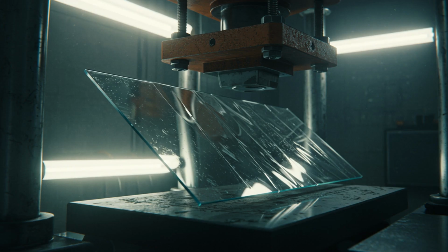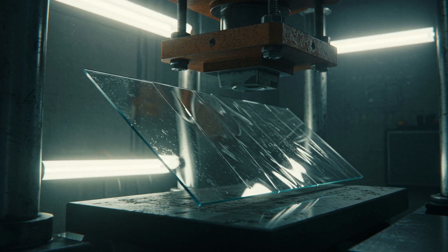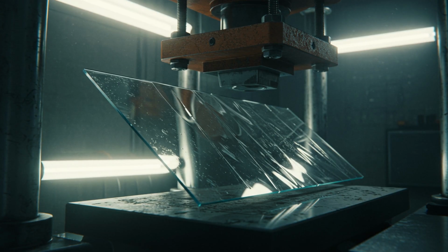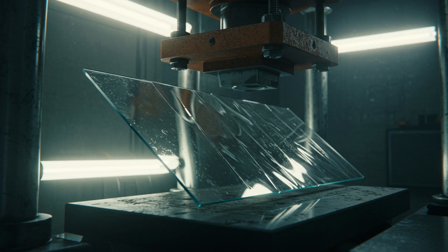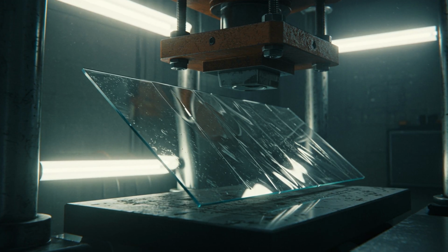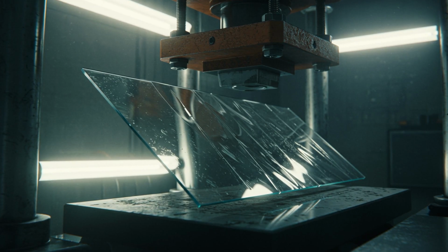Before any glass leaves the factory, it must prove its mettle. Quality control is a brutal process. Samples are taken from the line and subjected to impact tests, where heavy steel balls are dropped from heights to ensure the glass doesn't shatter into dangerous shards. We check the optical distortion by projecting a grid through the glass. If the lines bend even a fraction of a millimeter, the sheet is rejected and sent back to the furnace